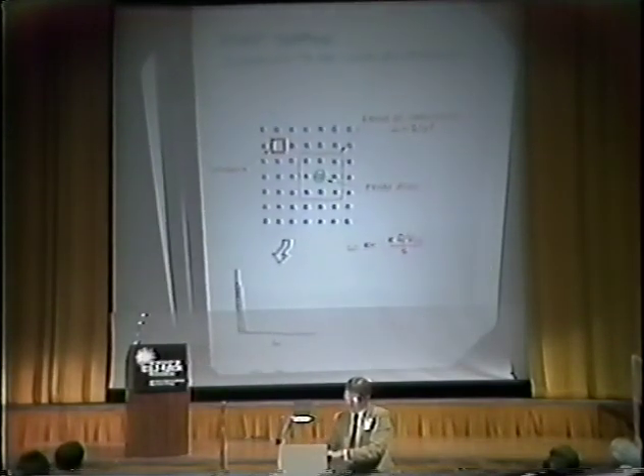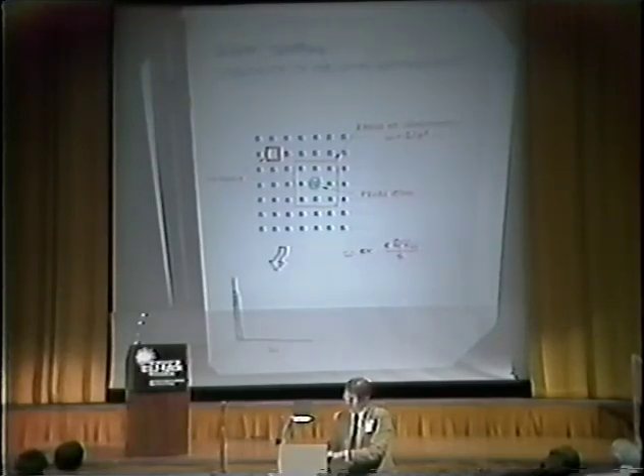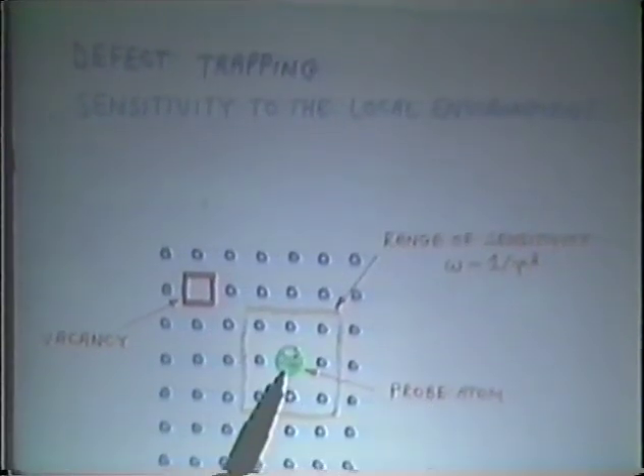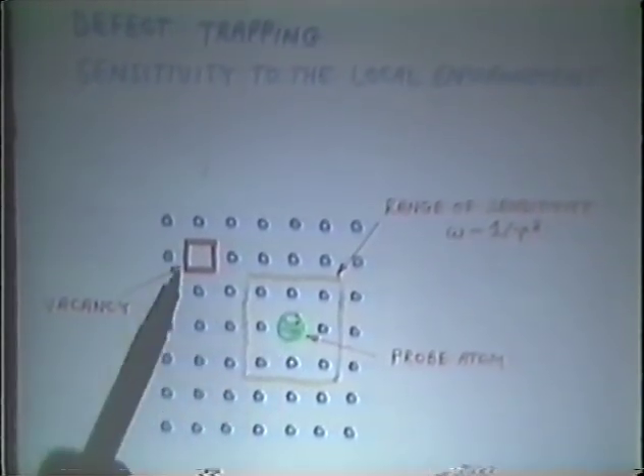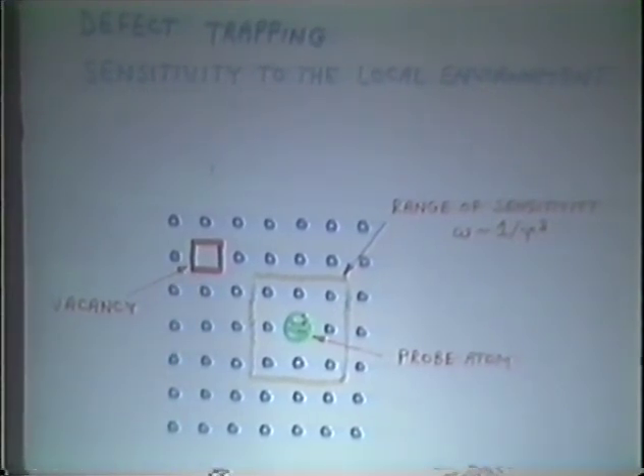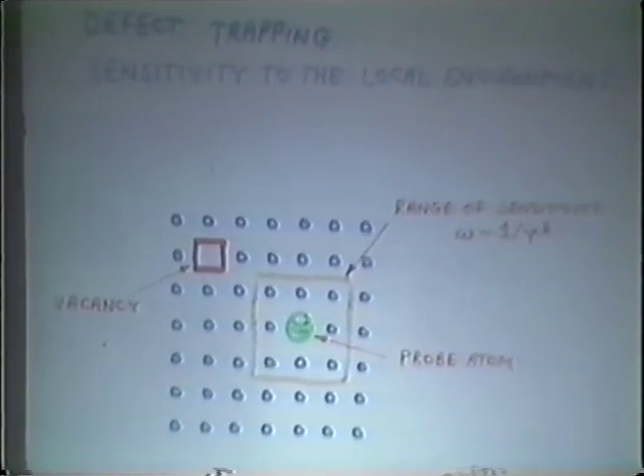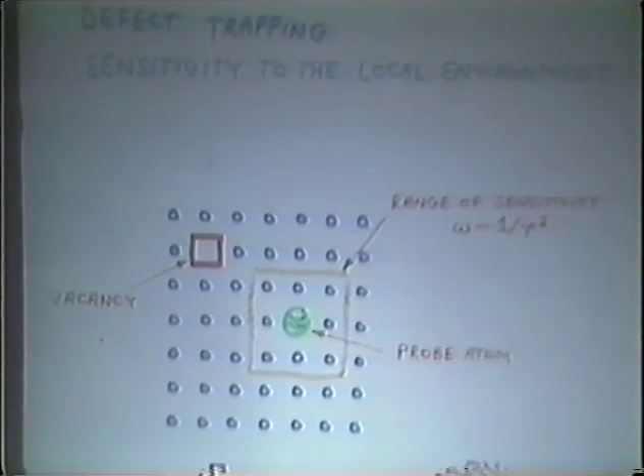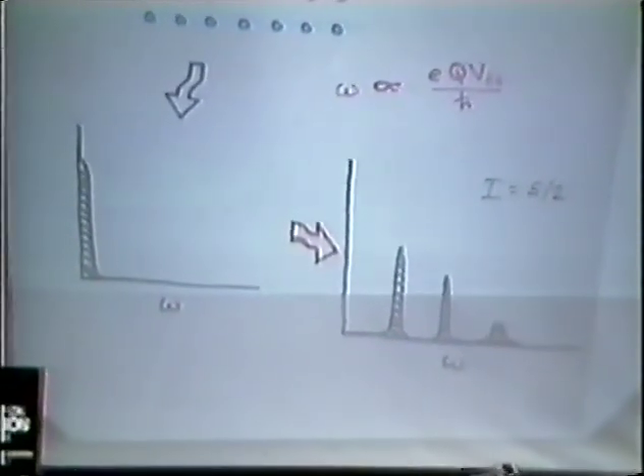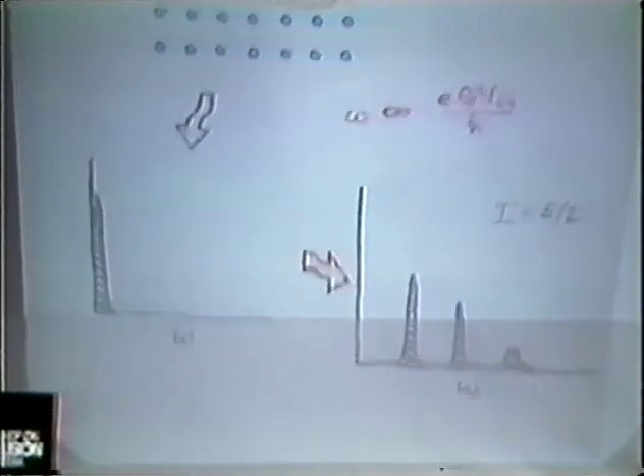following kind of approach, which has been exploited quite a lot in Europe. I introduce probe atoms into the solid by diffusion, and then produce lattice vacancies, such as shown here. Then, if the vacancy is far away, the probe nucleus is not sensible to the disturbance caused by the lattice vacancy. However, if we warm this damaged sample up, and the vacancy moves and traps next to the probe atom, as shown here, then you'll see an appreciable precessional interaction. So we can use these frequencies, there happen to be 3 Fourier components for a spin 5/2, as a signature, if you like, for a specific lattice location.